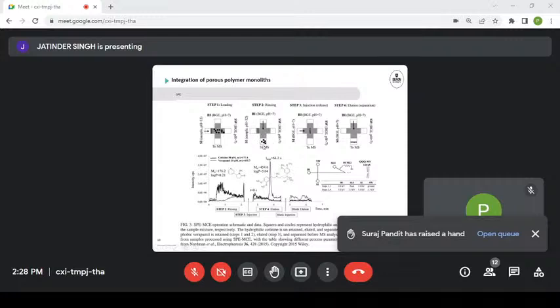So the stationary phase could be washed from all contaminants, or at least the part of the stationary phase that was at our cross intersection. Then the background electrolyte came to first elute our compounds of interest into our separation channel, and then change the direction of the flow to inject into the mass spectrometer. And you can see that they were looking at a couple of different pharmaceuticals by mass spec, and they indeed could concentrate them and purify them and get a much clearer signal after cleanup with solid phase extraction on the microfluidic device than before.